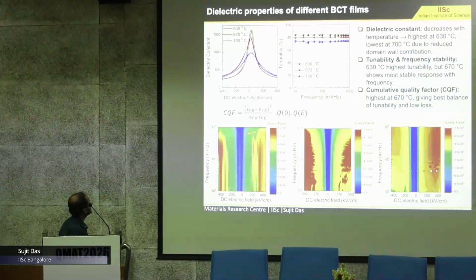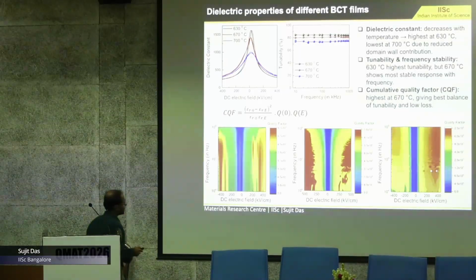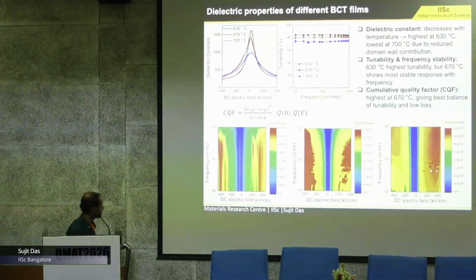And further we calculate this cumulative quality factor using these equations, which is important for bias tunability as well as the efficiency of these devices. And we found, interestingly, the film grown at 670 degrees C showing the highest CQF values, almost 10 to the power 4, with respect to the films grown at 630 and 700 degrees C.